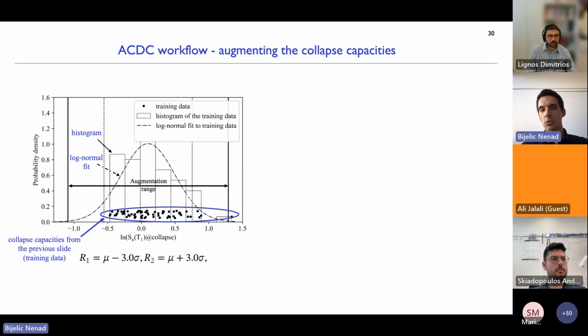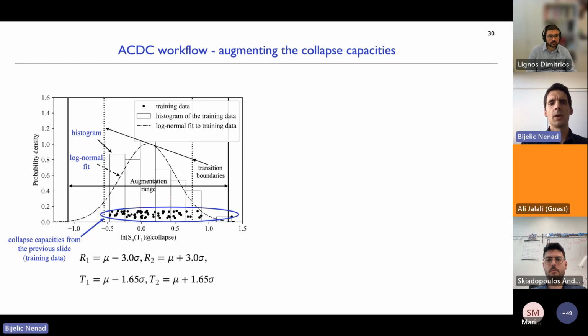Also on this plot, I showed these transition boundaries. I'll explain them a bit later, but basically we place them here in a way that they cover about 90%, so plus and minus 1.65 sigma from the mean, such that that range is where you would expect most of your data to be. Just to hint at this, in this range where you don't have data, it's a different situation as opposed to where you do have data if you do augmentation.